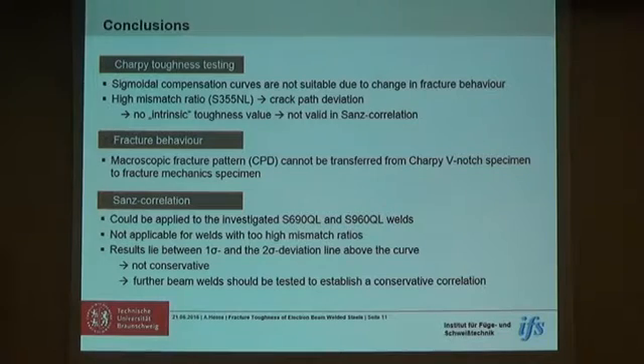And if we regard the question whether the Sanz correlation is suitable for the beam welded steels, we can say it could be applied to the investigated S690 and S960 welds. It surely isn't applicable for welds with high mismatch ratios, and as it doesn't show conservative results, another correlation has to be found.